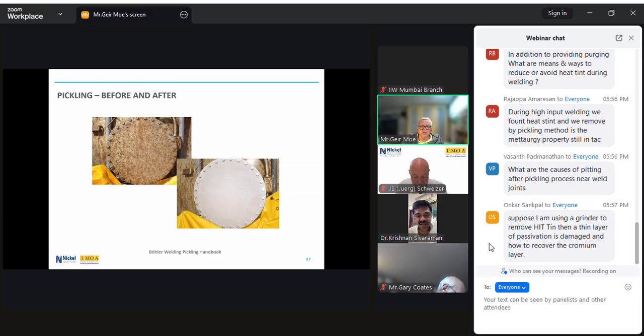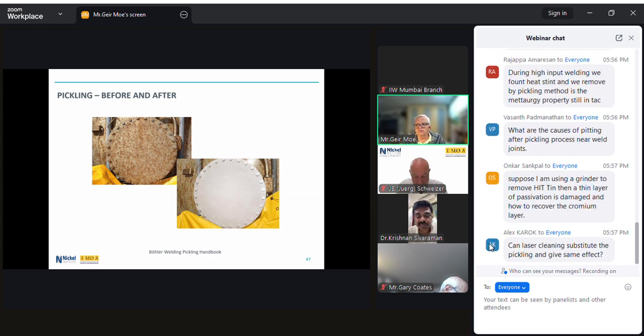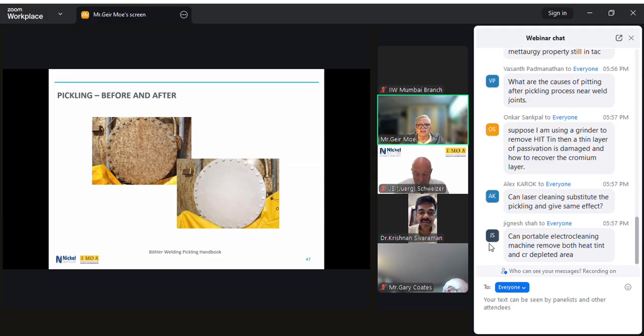With aluminum oxide grade, yeah, you could use any material to blast any stainless steel. The main thing is primarily not to use a blasting media that is contaminated with any kind of carbon steel, because then you would be embedding it into the surface. Even if you're blasting with a clean abrasive, it could be aluminum oxide, it could be garnet, it could be anything.